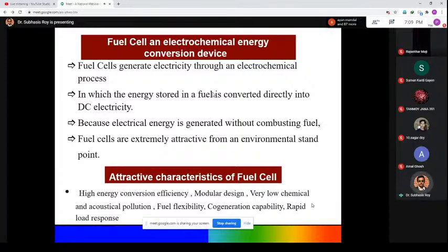And one of the major problems here is water generation. That means the side product, water, accumulates on the surface of the fuel cell's membrane. So we have to overcome this, otherwise the proper reaction will not happen at the interface. For this purpose, we have to prepare a properly working electrode which has a high hydrophobic property and repels the water molecules, so that water will not accumulate on the surface of the fuel cell.